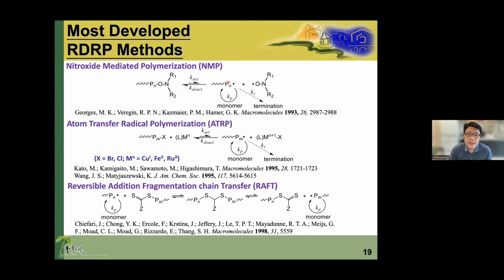So in that case, you can imagine if you can decrease the radical concentration 10 times, the polymerization rate decreases 10 times, but the termination rate decreases 100 times. So when you suppress the radical polymerization, you can suppress the termination rate so that the termination can barely affect the propagation and make the whole system look like, okay, living. So this is the mechanism they use.